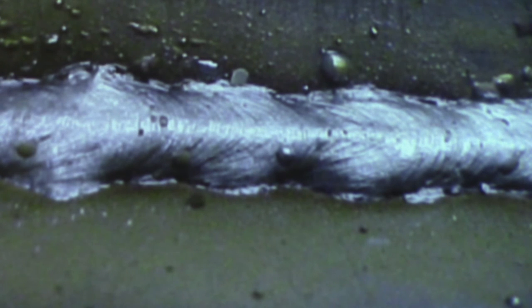And then I found a micrograph you can look at for lack of fusion. That's a really good picture here that we'll throw out for our last picture. And of course, it's located right on the toe of the weld. There's a ton of flaws in this weld here. This is a micrograph, so it's an etch. They cut the cross section out of the weld. And you can see the bottom right toe has no fusion with the base metal. You've got to remember this is zoomed in with a microscope. So that could have looked like it was okay without doing this testing. And then you can clearly see that it's not okay and that there could be a major catastrophic failure with this.